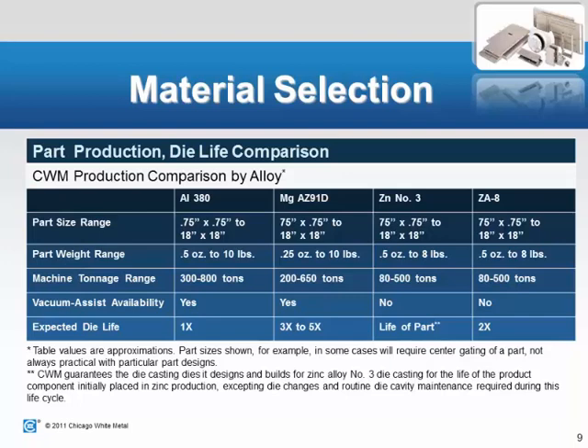ZA8 is another kind of a spin-off of zinc alloys. The 8 refers to 8% aluminum content that is in that alloy. It's processed very, very similar to the zinc family, but the higher aluminum content does allow it to have a little bit higher strength than the zinc families. And is, like I said, processed similar.